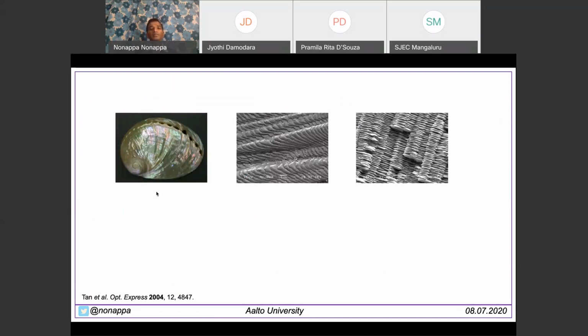And a combination of diffraction and interference can also be found. This is a two-dimensional material, not three-dimensional, but rather different from any other category, the mother of pearl. You can see beautiful but very diffuse color. Now, if you look at the surface of this, you will see not very well patterned grooves. And if you take a cross-section of this, you see even smaller structures of calcium carbonate, which have about 5% other organic polymer, like maybe chitin or some proteins, between these